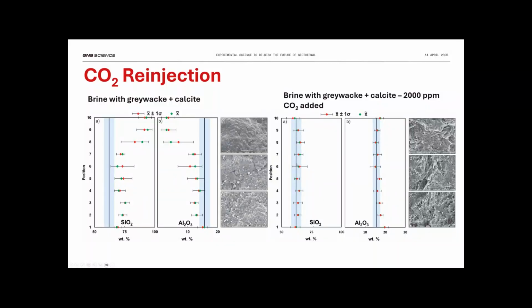And you can see that pretty much they all lie slightly above the average, but generally compared to this one here, there's no silica scaling, and the aluminium is indistinguishable from the unreacted rock. And then when you look at the SEM images, you don't see these spherulitic precipitates.